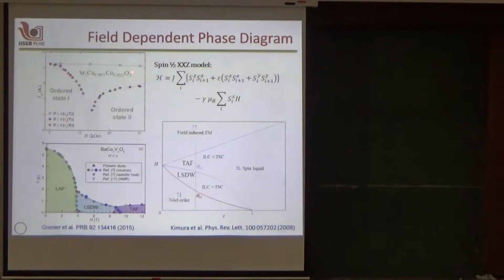So you see, this is now for 0.25% cobalt, and we see the same behavior, the transition disappearing and the new phase appearing. All this data is unpublished so far. So we tried to understand what's going on here, and we found that this is actually seen in another cobalt based system. This is an example of an Ising like chain. And here they have seen that at low temperatures there is a cascade of transitions as a function of magnetic field, and these are transitions from this longitudinal antiferromagnetic phase to a longitudinal spin density wave to a transverse antiferromagnetic phase.